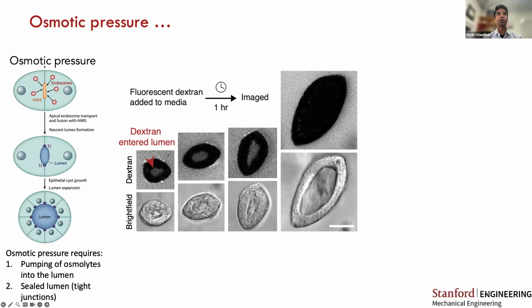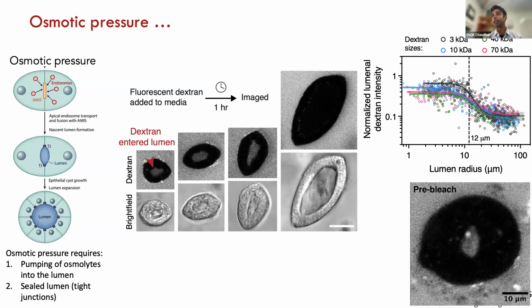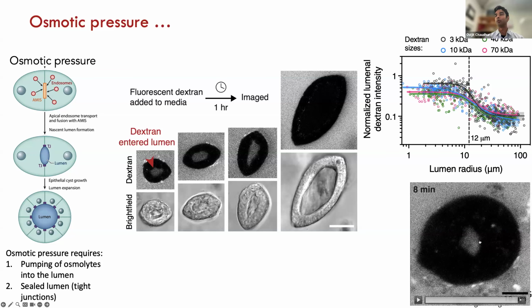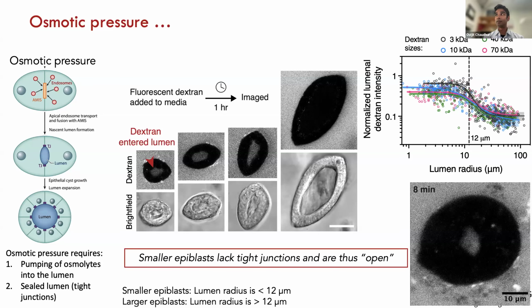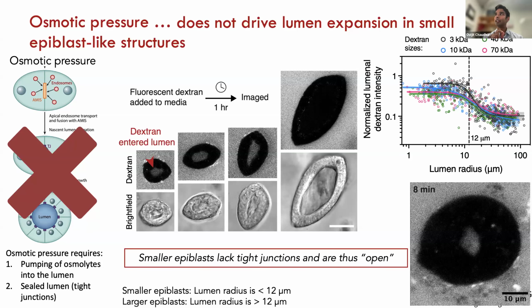What we see is that the fluorescently labeled dextran enters the lumens quite readily when the structures are small. So for smaller lumens, it appears that the junctions are not tight, they're actually leaky. And indeed, we can confirm that using bleaching studies. We bleached the fluorescently labeled dextran, and within minutes, fluorescent dextran from the media enters into the lumen. So what this tells us is that we don't have tight junctions in these smaller epiblast-like structures, so osmotic pressure gradients cannot drive lumen expansion.